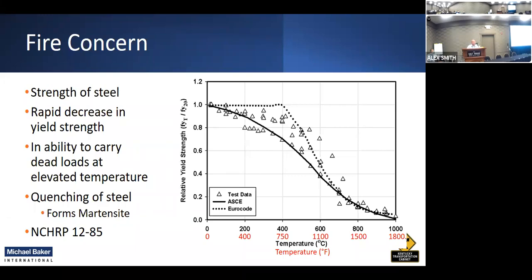Of course, the concern was the fire and what it did to the steel, what it did to the concrete, and what the strength of that steel came out to be after that. Of course, we knew that there was a rapid decrease in yield strength depending on how hot that fire got, and the inability to carry the dead loads at elevated temperatures. Quenching of the steel was our biggest concern, because we did not want that to form martensite, which makes that steel really brittle. And once it gets brittle, it can crack like glass. So that was our biggest concern.